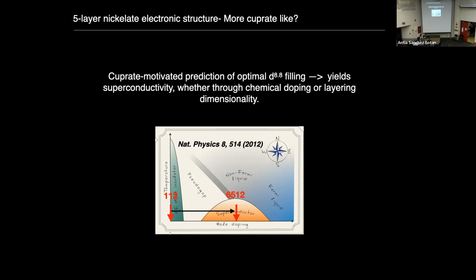But what we thought was very shocking, of course, was that this naive, if you like, cuprate-motivated prediction of optimal doping at d^8.8 had now given us superconductivity in 2 different nickelates by, again, using that simple analogy, right? Both in the 112 or infinite layer compound, which you get here through chemical doping in that material, or you can also do a layering of the dimensionality, and that's how you get to this point for the 5-layer or 0512 compound instead.